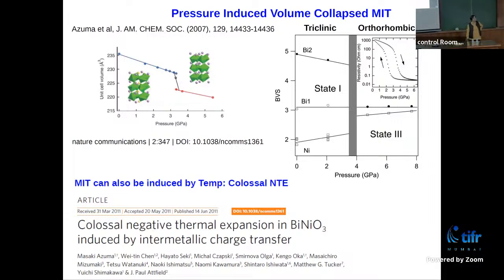What they did, they took this insulator and put pressure, and then they could drive an insulator to metal transition at a critical pressure of 3.5 gigapascal and with a volume collapse. Volume collapse is 2.5%. And then what chemists do quite a lot is called bond valence sum. By this bond valence sum, they find that at ambient condition there are two different sites of the bismuth, bismuth 1 and bismuth 2. And they proposed a picture, which I will show you a little later.